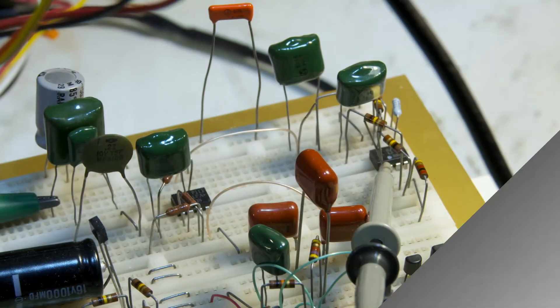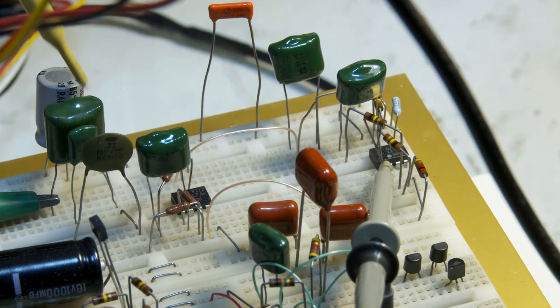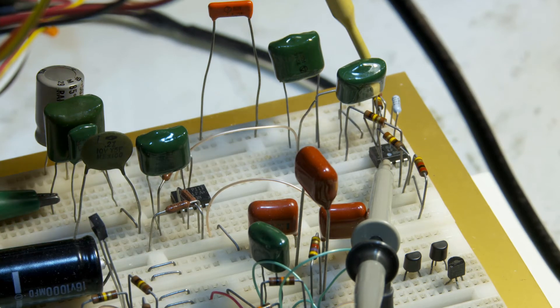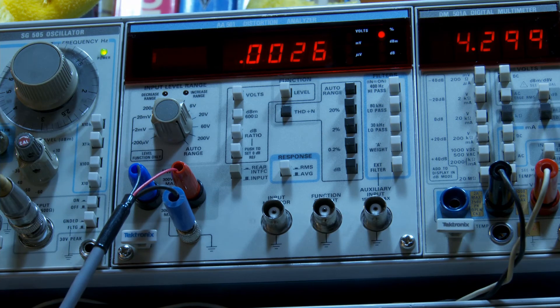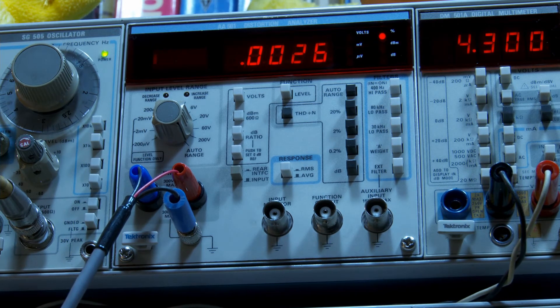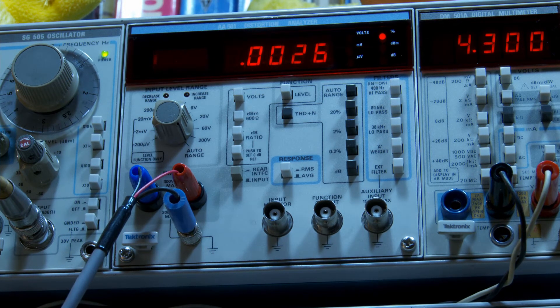Now let's change out the capacitors to polyester film of similar value. We see our distortion has dropped by two orders of magnitude to vanishingly low levels.